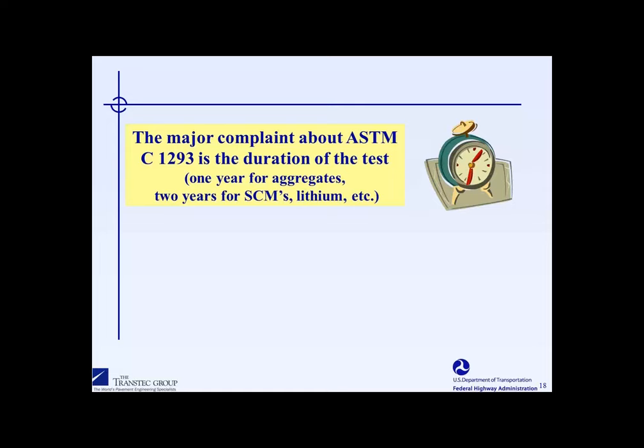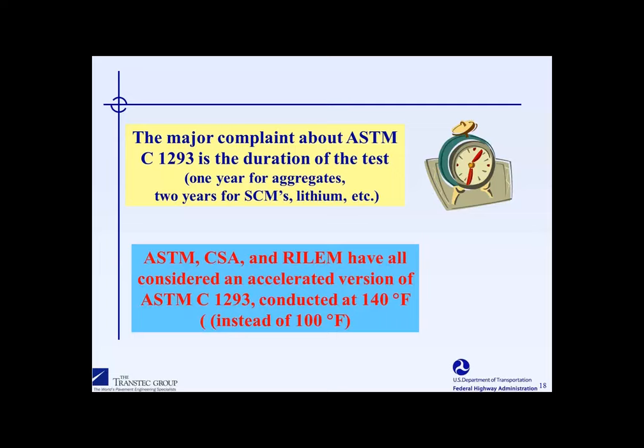So with regard to the ASTM C1293 test, the biggest complaint is it takes too long. 1 year for aggregates, 2 years for anything else. And there have been efforts within ASTM, Canadian Standards Association, as well as European research groups to try to accelerate the test by increasing the temperature from 100 degrees Fahrenheit to 140 degrees Fahrenheit. And the intention here, and there were some earlier reports suggesting that perhaps the test can be run in 3 months instead of 1 year for testing aggregates, and maybe only 6 months would be needed instead of 2 years for testing SCMs.